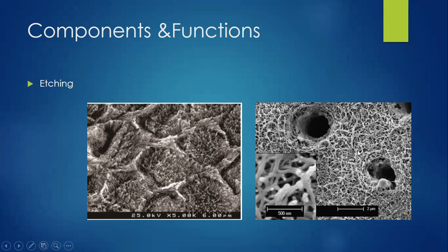After phosphoric acid use, H3PO4 leads to complete removal of the smear layer and demineralizes the intertubular dentin up to 3 to 5 micrometers. Because when we use H3PO4, it does not modify the smear layer, it removes it. So there is complete removal of the smear layer and hydroxyapatite crystals. We'll discuss later why hydroxyapatite is important. It also removes smear plugs and dissolves the peritubular dentin, and the open dentinal tubules acquire a funnel shape.